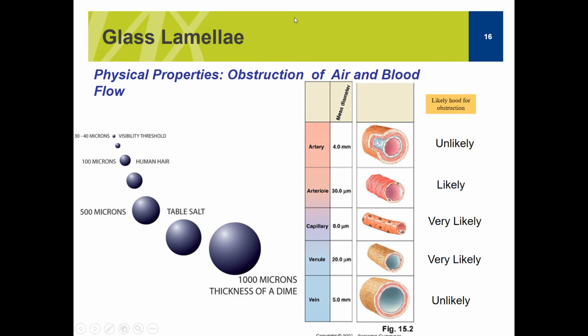You can see that the capillary is very small, 8 microns, or micrometers, in diameter. So 2 or 3 glass lamellae, if they are injected, can block that right away. And what happens when this happens? This can cause multiple strokes or lung collapses. Now, this second slide really gives you an idea of the size, how big a micron is, and how small these glass lamellae are.